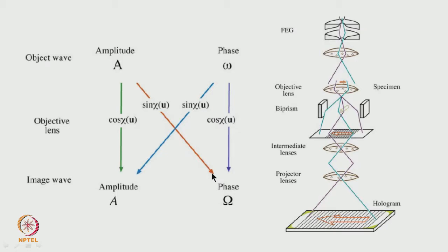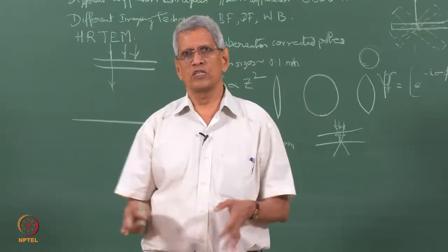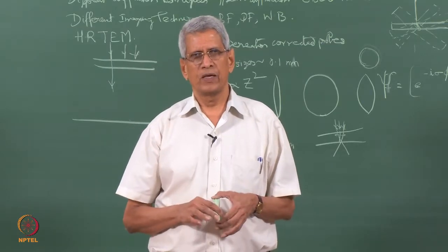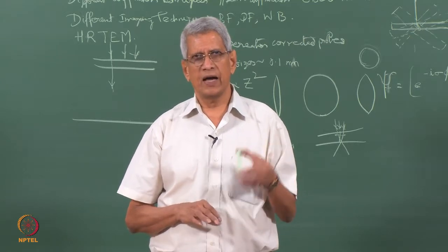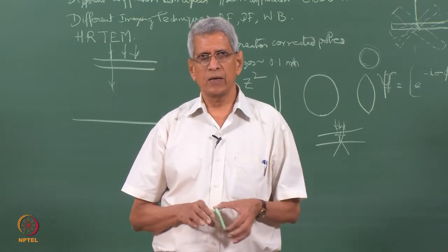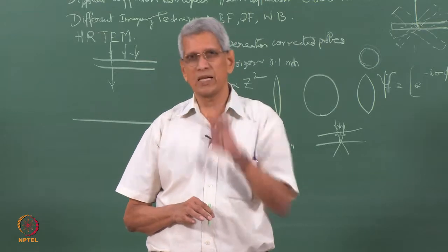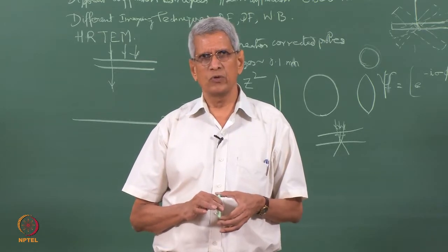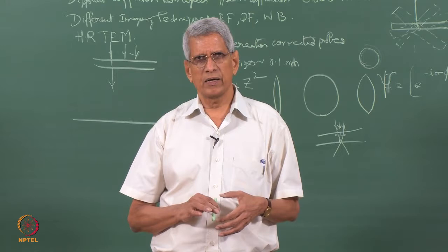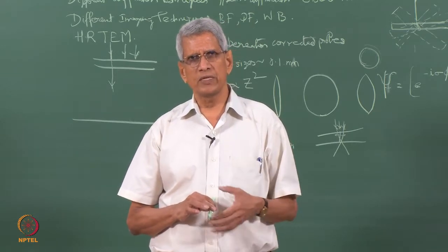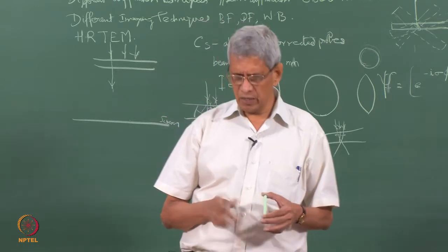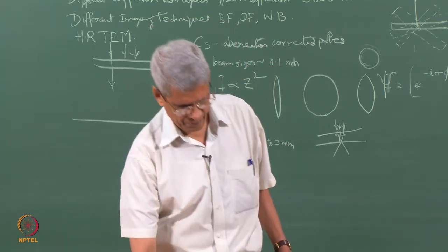But the advantage essentially is that from one micrograph, one hologram, we can get complete information about the phase and the amplitude. Whereas in high resolution microscopy, as I mentioned, to get correct structure information, we may have to do contrast matching for at least a few images taken under different defocus conditions.